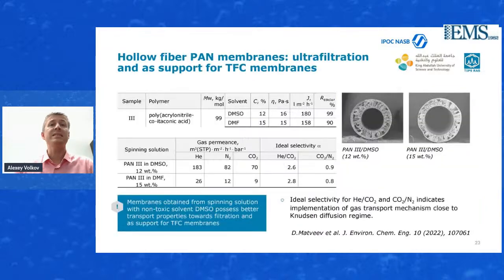And in that case, we make a comparison of DMSO and also DMF, and once again, based on the data for the flat sheet membranes, we were also able to get better performance using DMSO instead of the DMF in terms of the hollow fibers, making ultrafiltration range membranes, or also using that as a support for the gas separation membranes.